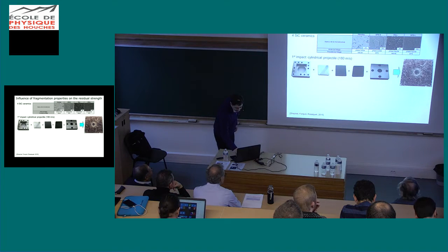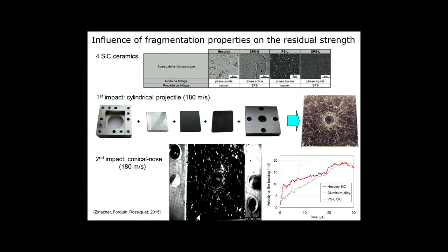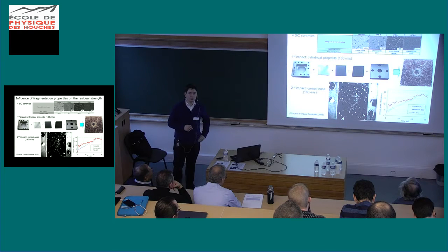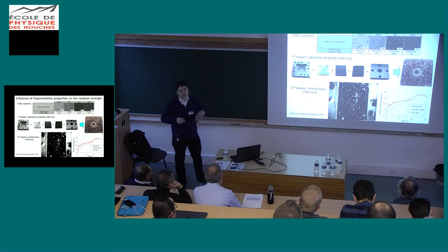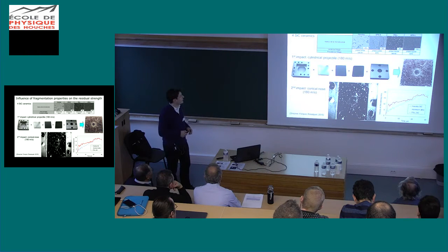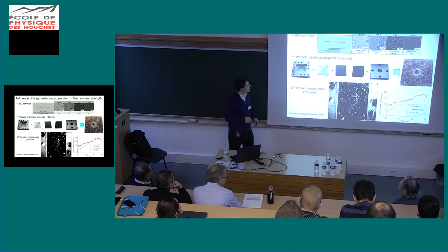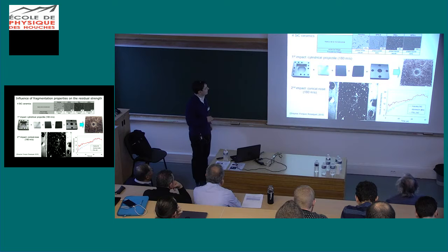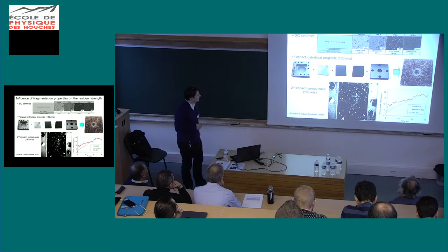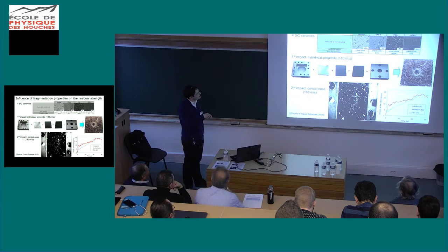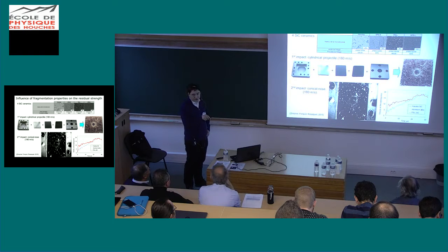Other important point. So why should we investigate fragmentation? Maybe we could say, okay, the ceramic fragments and we don't care how it fragments. But in fact, it is important, and I think this configuration can explain that to you. In this configuration that was presented by Marielle yesterday, ceramic was sandwiched between a front steel plate and aluminum backing, and was first impacted with a cylindrical projectile, so we generate an intense fragmentation process you can see here.